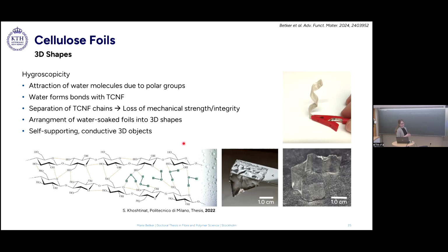And so I took my foils and actually I took them out of the water bath, so they are still soaked with water. And then I put them into three-dimensional shapes and simply let them dry overnight. Nothing else. And this is how you can make these three-dimensional shapes. So this is, again, this multi-layer foil we saw before. And you can see it's freestanding, it's also self-supporting, and it's also conductive. Exactly. So now you saw that you can make actually very nice things by only using spray coating and cellulose.